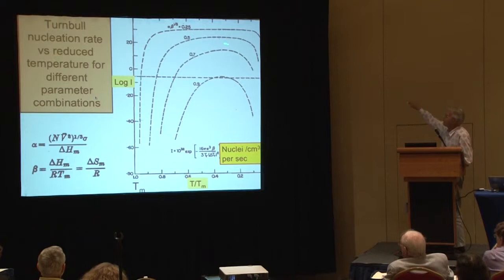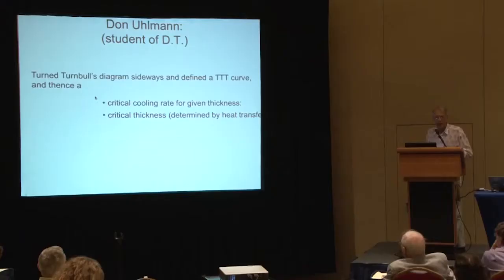His time temperature transformation or nucleation rate here as a function of reduced temperature, reduced by the melting point, set the stage for all sorts of other work in the area, including that by Don Uhlmann, who was one of his students, who turned Turnbull's diagram on its side and gave it a name, the time temperature transformation curve, and defined the critical cooling rate, which you see here.